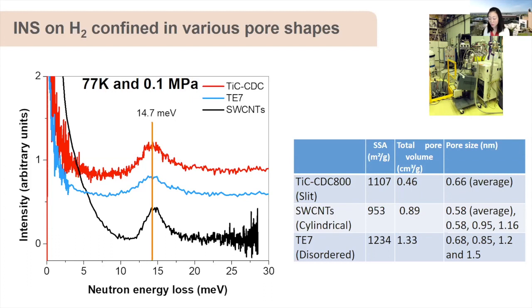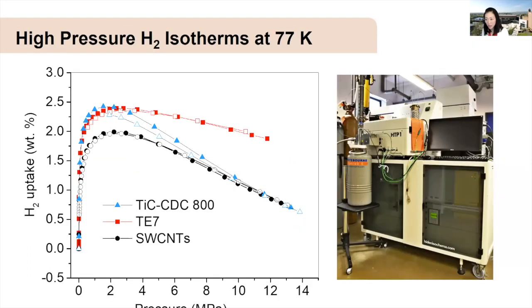Yeah, we just need to focus on controlling and narrowing down the pore size. And another important piece of information we really care about is how much hydrogen the material can store in total. So we carried out high pressure gas adsorption on this equipment in the lab. The maximum hydrogen uptake is about 2.5%, and the single wall carbon nanotubes have a slightly lower hydrogen uptake due to their relatively small surface area and low pore volume.